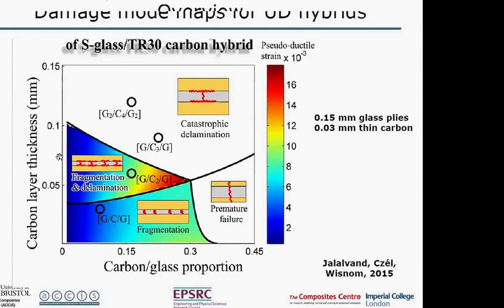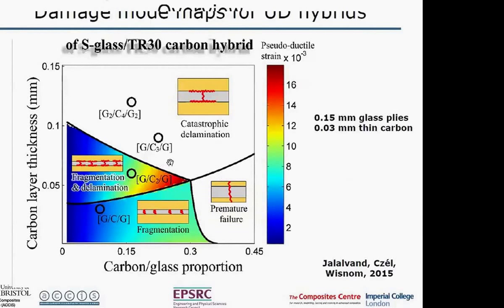But if we have sufficiently thin carbon and not too much of it, then we can get either this pure fragmentation mechanism or this fragmentation with localized delamination. And that's what gives us a pseudo-ductile response,